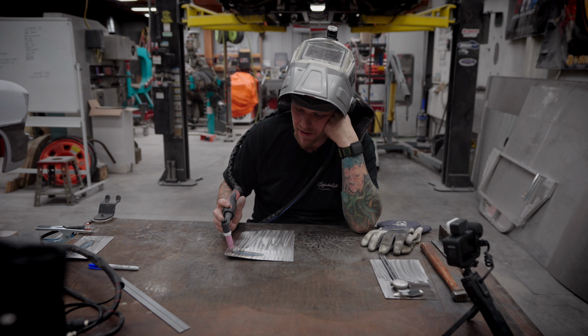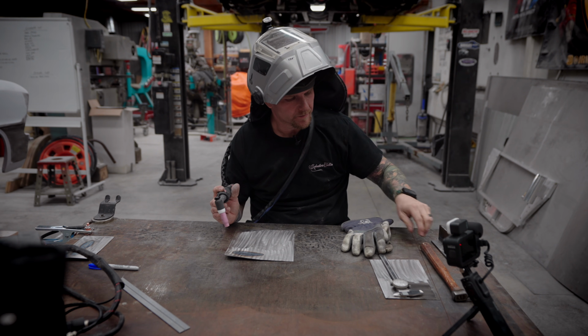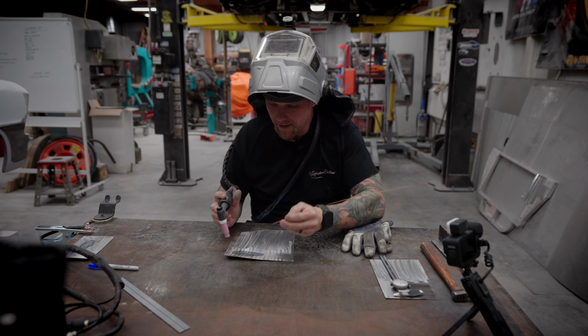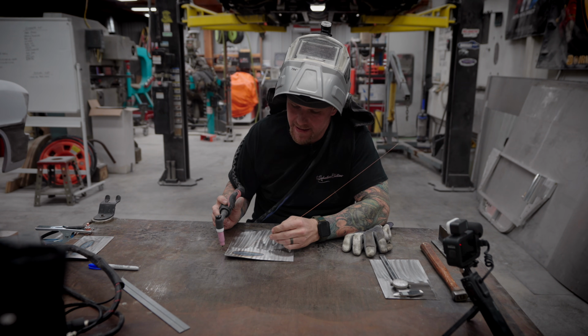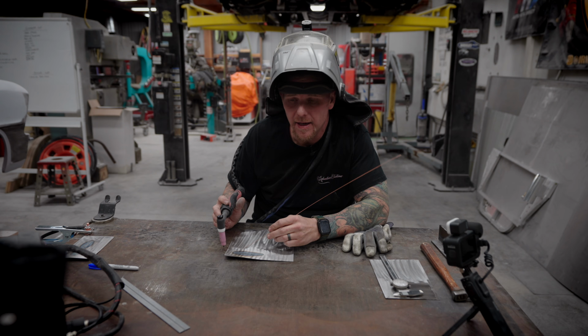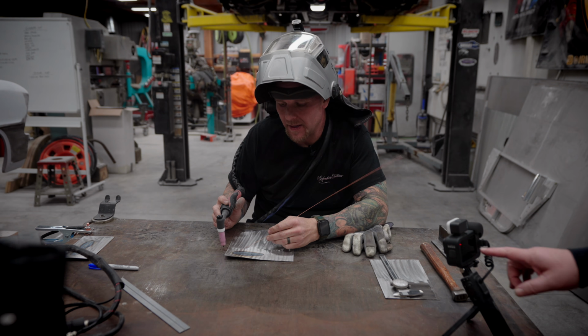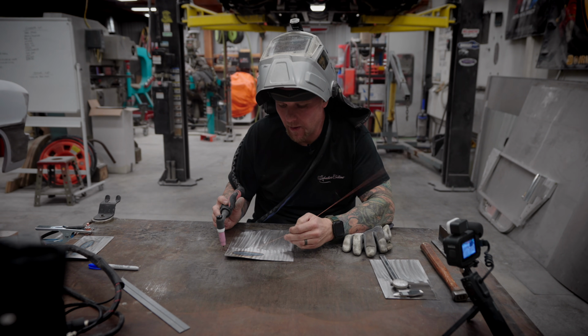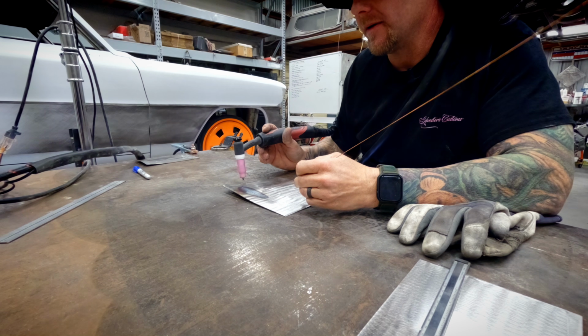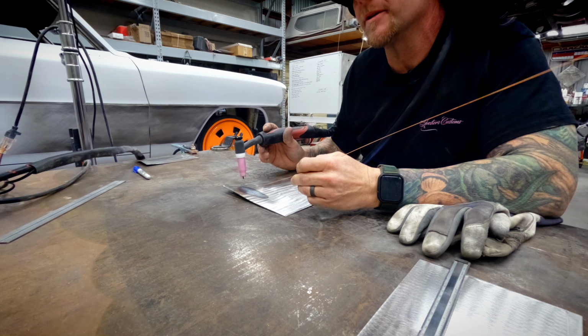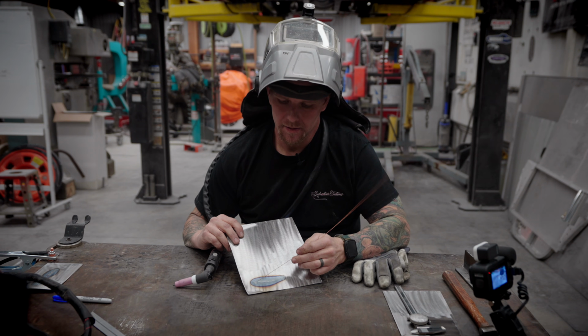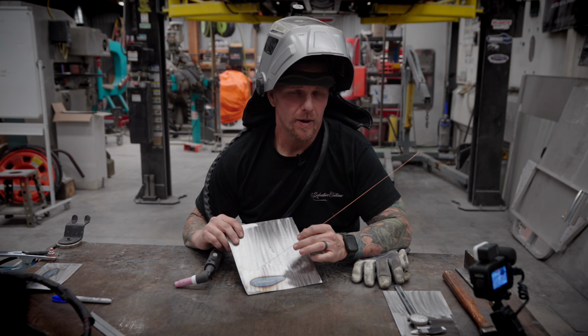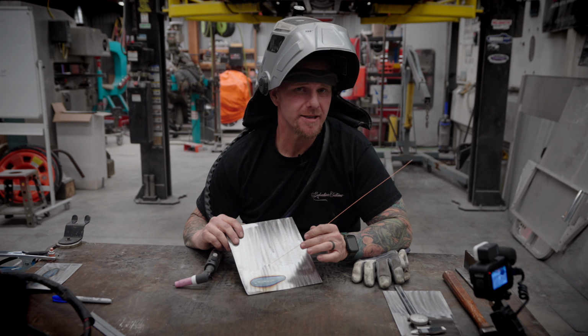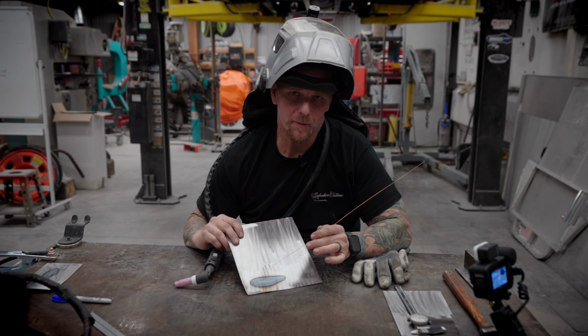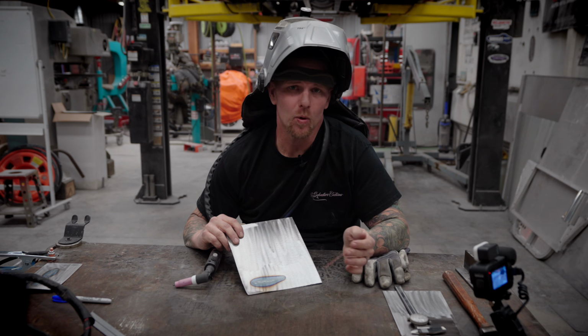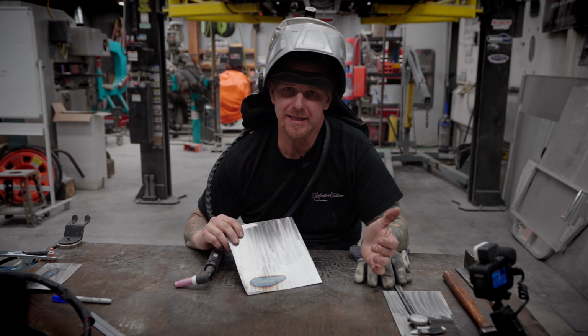And when we stop and we look at our heat affected zone, this heat affected zone, as I'm showing you guys and staying in one area, you can see how much more it has grown side to side. There's going to be way more warpage. Really, what we want is to be about the width of where we are right here in the middle, which is about an inch. As we started the arc, we stayed here for too long. When it comes to sheet metal, you want to get in and get out as efficiently as possible, and you don't really want to be sitting and hovering in one area like you would with standard tubing or 3/16 steel.